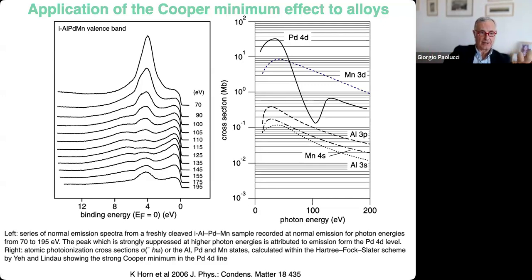Then you compare the behavior of the 4 eV peak, which you can see goes up and down when you change the photon energy. And then if you look at the relative cross section, you see that the minimum occurs at 100 eV. If you look at the right-hand side of the picture, this is exactly where we see the minimum in the intensity of the 4 electron volt peak. So we can safely say that that peak is mainly associated with palladium electrons. So by using this trick, you can actually understand the weight of the information of the bonds.